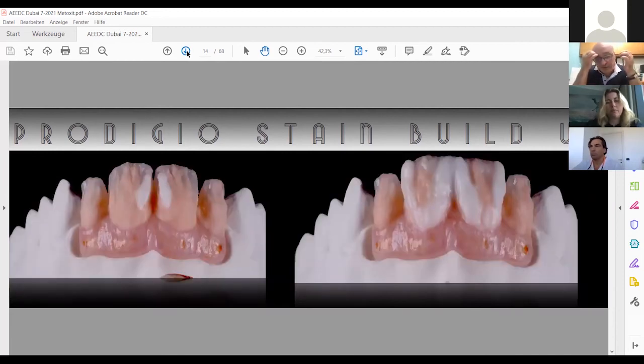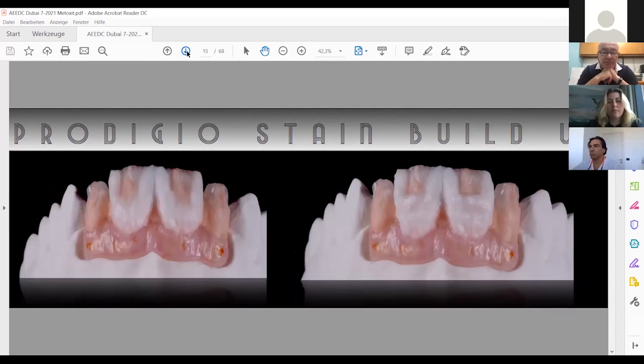Minimal layering. If you use a porcelain, very little dentin, some enamel, in one bake. I prefer to have my final shape. Next. And after I place my enamel or effect or any translucency, I play with a lot of translucent material, because zirconia itself, even if it has a nice translucency, is still a monolithic block, and sometimes you need to increase the translucency, or sometimes you need to increase opacity, depending on the final shade. Next.